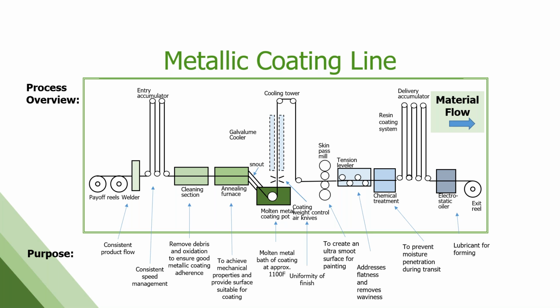Then it would go through a skin pass mill and some tension leveling. That gets a nice smooth surface, takes any shape out, so you have a very flat product at the end. And then you can apply some chemical treatments and passivate it to help prevent rust, and maybe a thin resin coating. If it's going to be a bare product, we put a thin resin coating on it to prevent fingerprinting and to aid with forming downstream. And then out the exit end of the line.